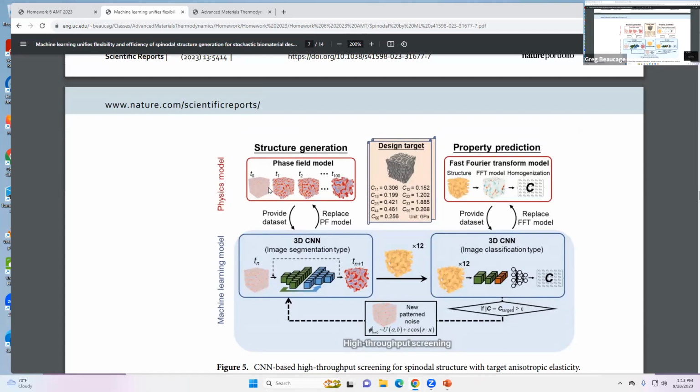Maybe it's some part of the point, but anyway, in that phase field, he can simulate these things as a function of time. So he's got 6,000 of them, and each one of them has a time sequence up to 100 time steps, whatever a time step is. He just lets it evolve. He starts with a random concentration, then plugs in those Cahn-Hilliard equations with the gradient, and then it decides where it goes. And he takes that as the next starting point. So each time he takes a starting point and calculates, that's a time step. He does that over and over and over again. And this thing decomposes and looks just like Cahn-Hilliard.